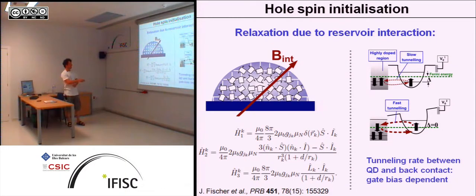Forget about these terms. The important part is that the first term has a delta function. So the coupling between carrier spin and nuclear spin here is only exactly at the position of each quantum dot nucleus. The next term is again a carrier spin and nuclear spin coupling, but here you have these normalised direction vectors. So in the end, what this results in is an orientational dependency.